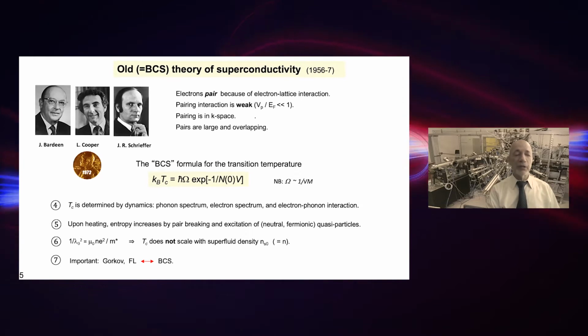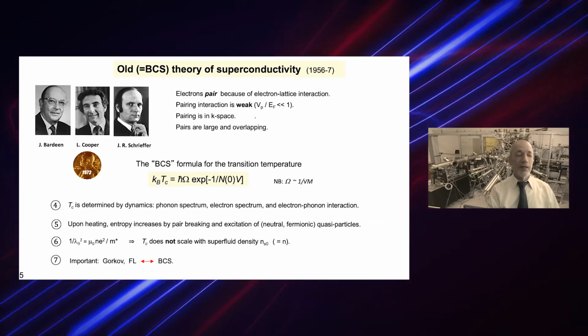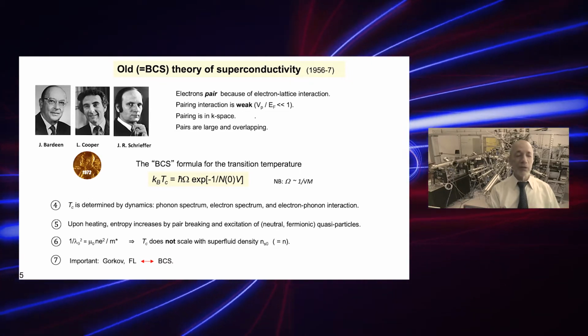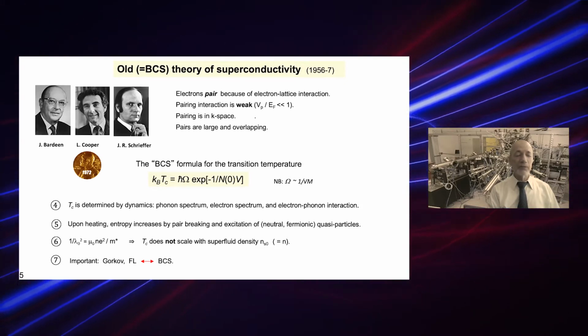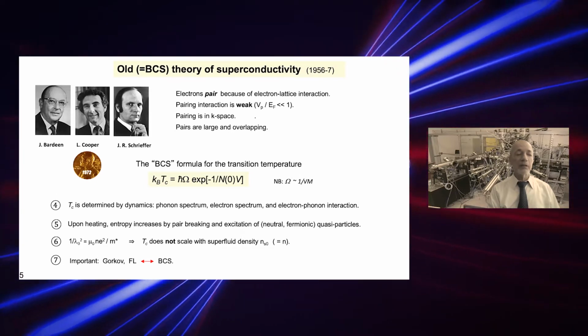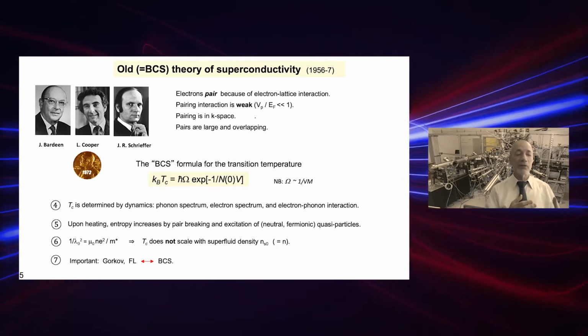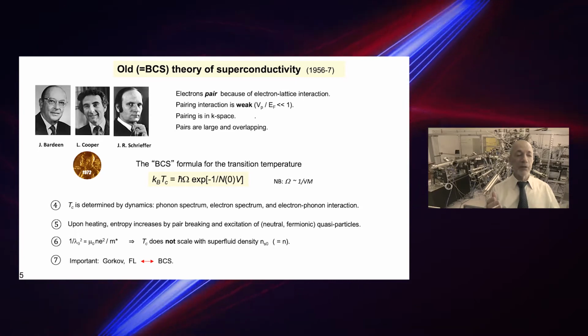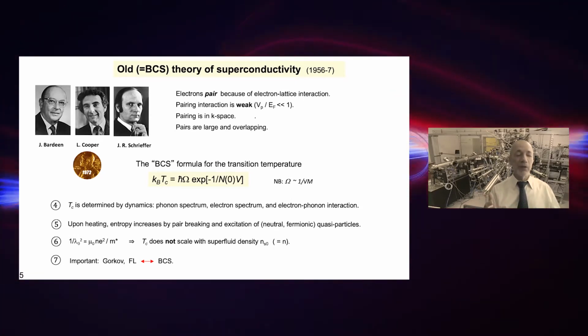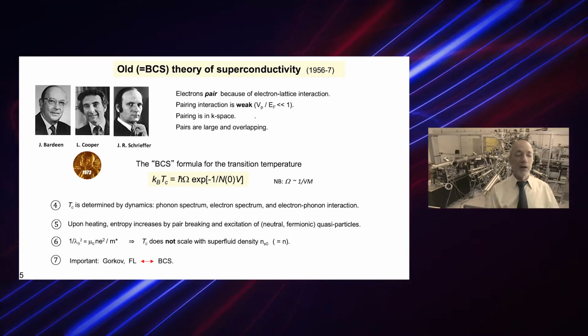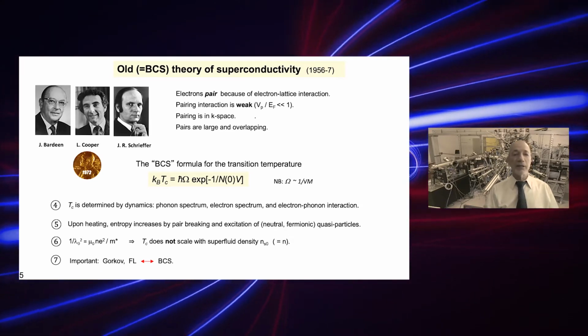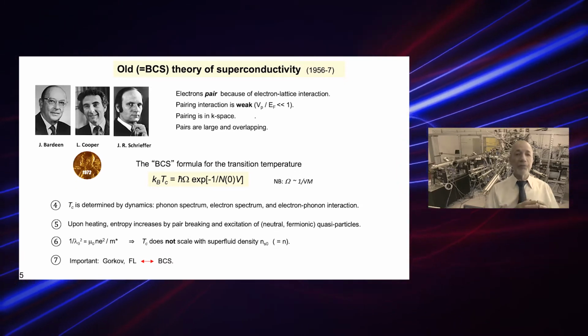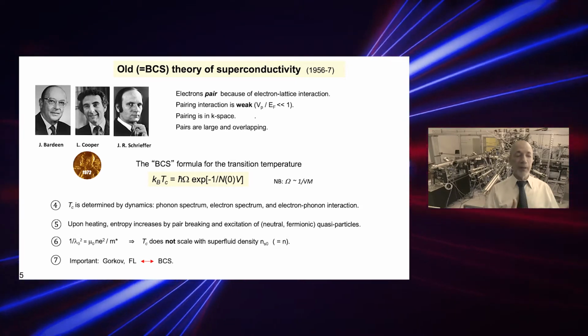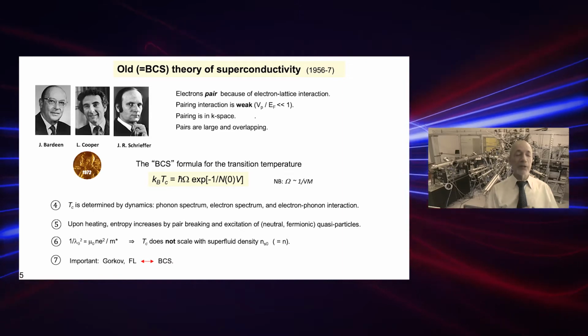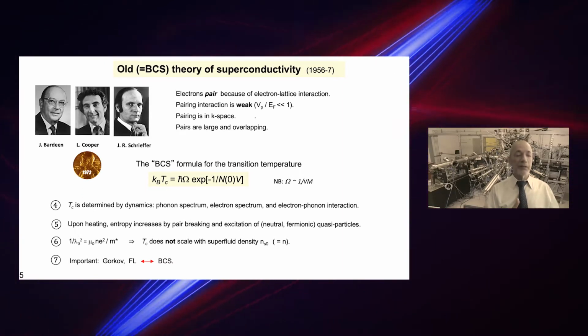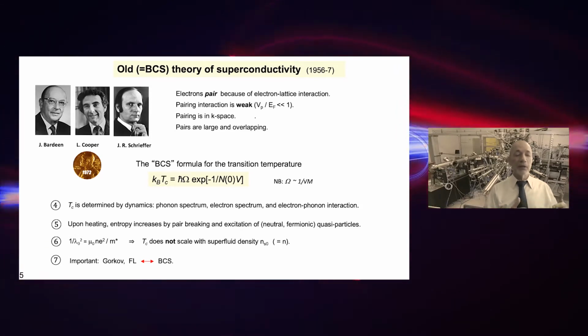After many failed efforts, including by the likes of Einstein, Bohr, Pauli, Heisenberg, etc., the puzzle of superconductivity was solved eventually by Bardeen, Cooper, and Schrieffer. Their key postulate was that electron-phonon coupling causes a weak, effective, attractive interaction that pairs electrons in the inverse space, in K space. These Cooper pairs are large. The partners can be more than 1,000 unit cells away, so the pairs overlap and they stay entangled. Again, I have singled out a few essential details that are important to what follows. First, TC is determined by the dynamics: the electron spectrum, the phonon spectrum, and their coupling, or the interaction potential. Second, at 0 temperature, the superfluid density should be equal to the total electron density, and it is basically unrelated to TC.